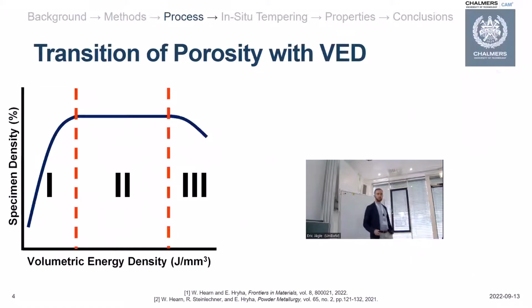And then finally, in terms of the parameters we looked at, we produced specimens for both of the machines and materials at VEDs of 60 to 200, using a set laser power, hatch spacing, and layer thickness. And for the specimens produced on the M290, we also produced these specimens at preheating temperatures of 25, 100, and 180 degrees Celsius.